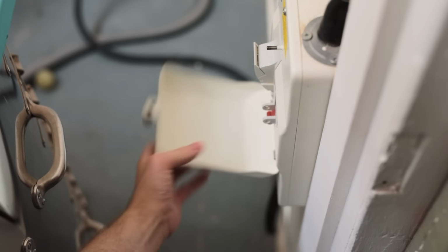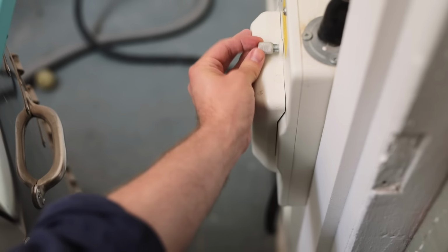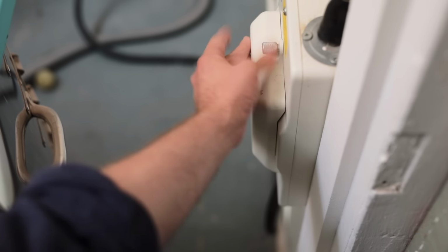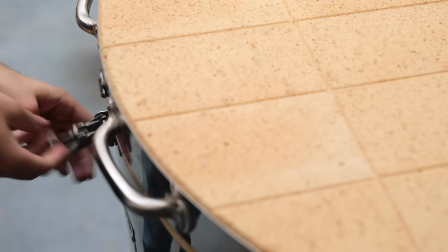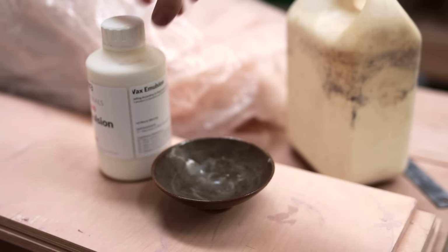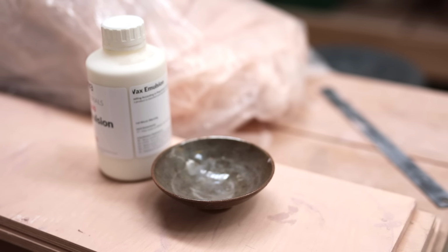Next on the list is waxing, which is perhaps the quickest and easiest job. Wax on the bottoms of the pots ensures that glaze won't adhere to them when they're dipped into it. If the bottom is glazed and is placed onto a kiln shelf and fired, the glaze melts, creates glass, and fuses the pot in place, meaning the pot has to be ripped off the kiln shelf or smashed off with a hammer, both of which result in damage to the vessel.